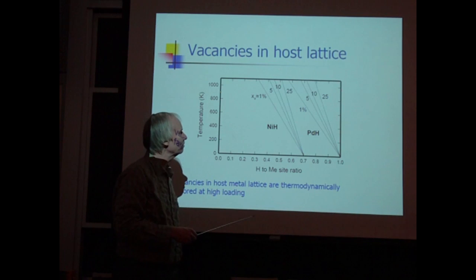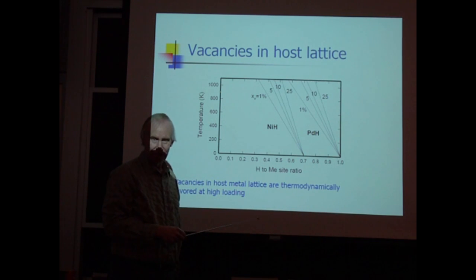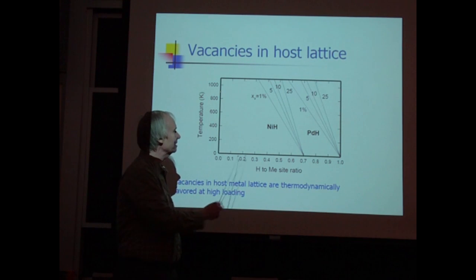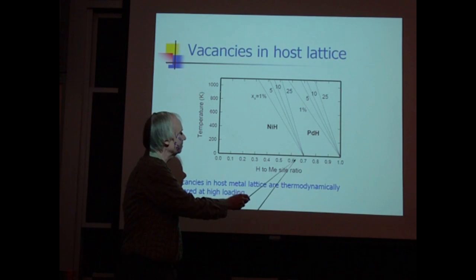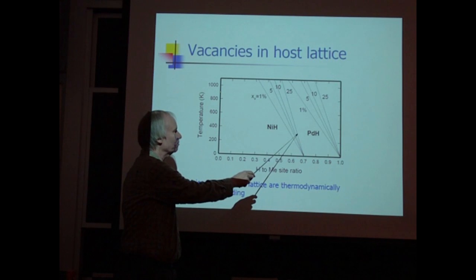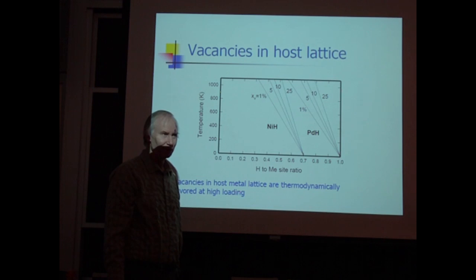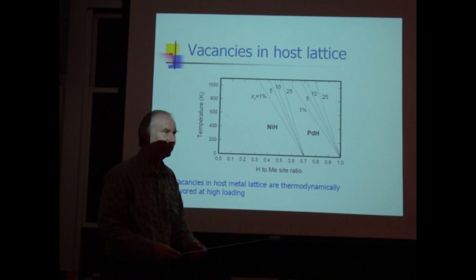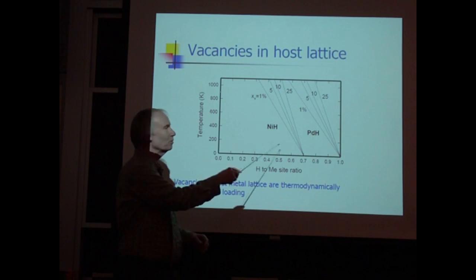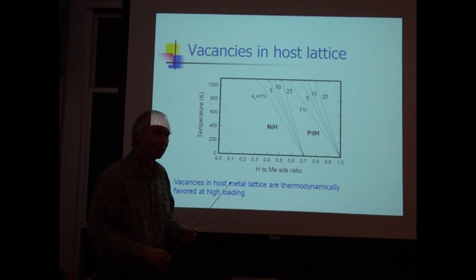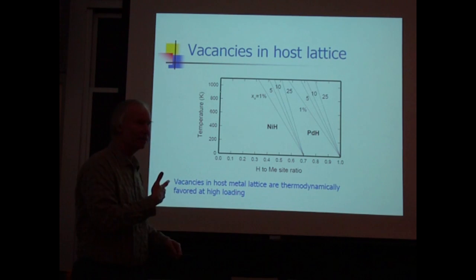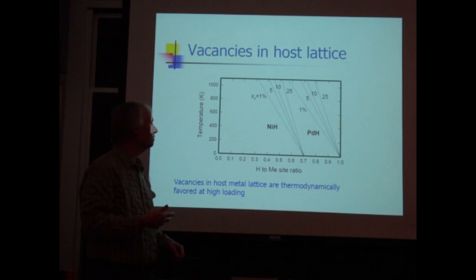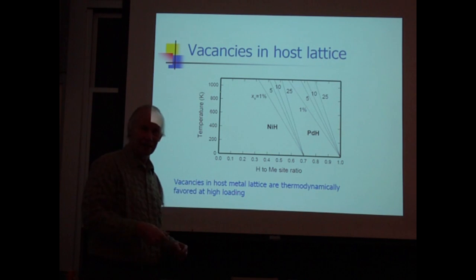Nickel hydride works the same way. Hydrogen loading stabilizes the vacancies. The only thing is that in the case of nickel, the stabilization is more effective, so you'll need to be at a loading of 0.65 or thereabouts in order to stabilize vacancies in nickel. This will be much more important to us on Friday, but since we're interested systematically in metal hydrides and vacancies at the moment, having them both on the graph here is useful.